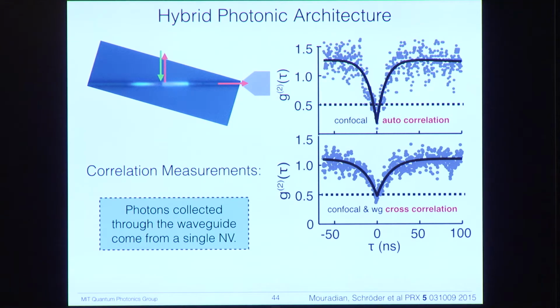And that is because, as I mentioned earlier, silicon nitride has a lot of background. So when we're exciting this waveguide with the green light to excite the NV center, we're unfortunately also exciting defects in the silicon nitride, which also produce broadband fluorescence, which we then collect, which reduces the quality of the photons that we collect.